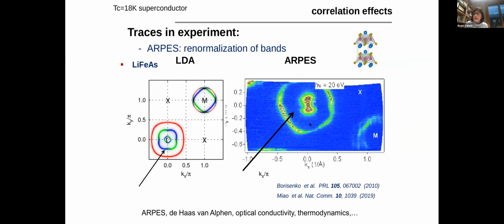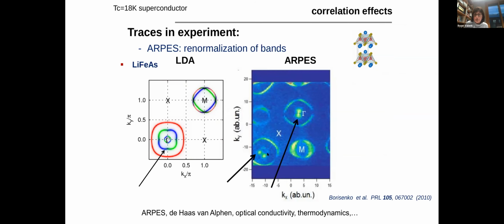As you can see, these are ARPES measurements from Borisenko and collaborators, and there are of course many ARPES measurements in the literature, but what I want to show you here is the Fermi surface around the gamma point, where one observes that the inner hole pocket is strongly renormalized with respect to what we obtain by doing, for instance, LDA calculations. The inner hole pocket shows a flower-like shape. So I'm showing here the experiments just to see this strong renormalization.